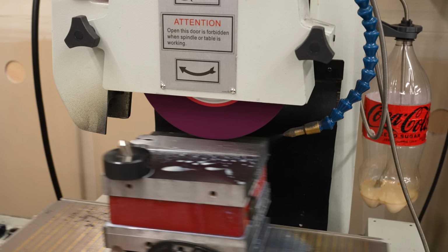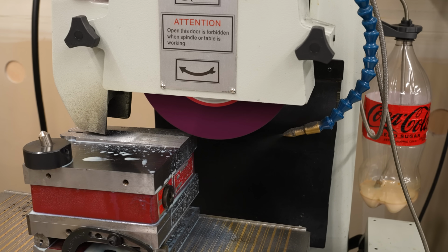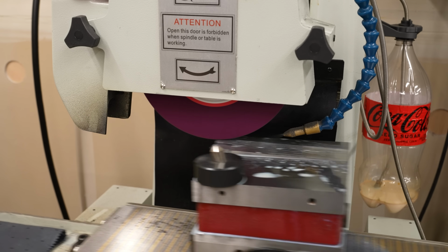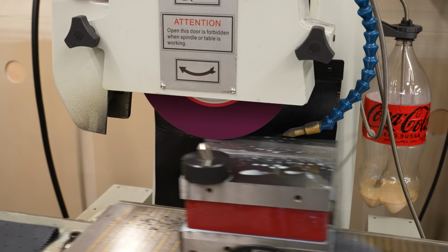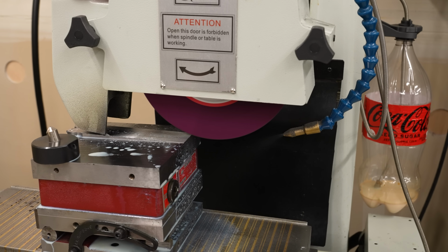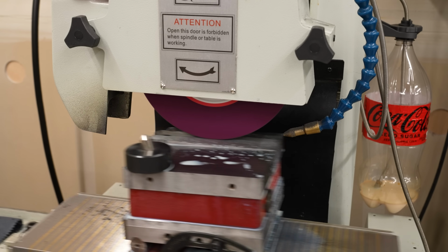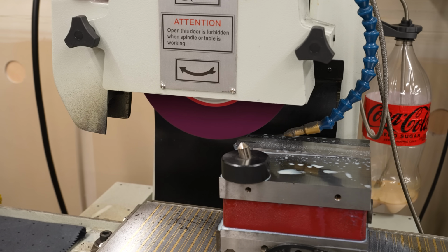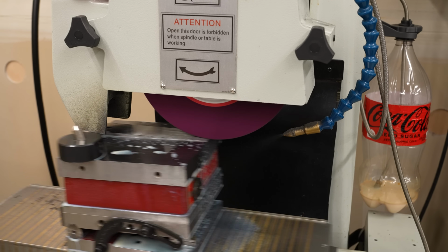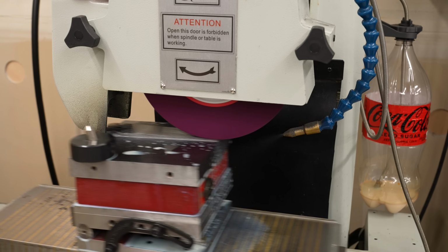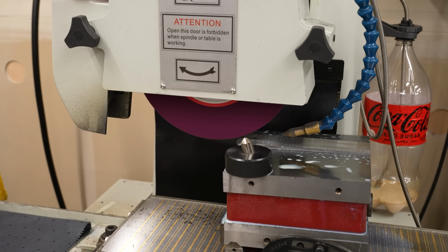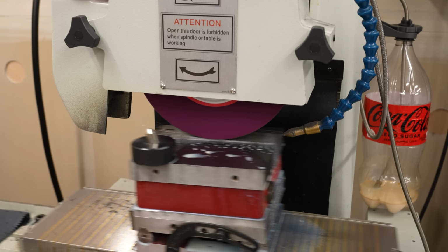The only way I was able to get this to work was to make the coolant mist very, very wet and to go very slowly. For a lot of the finish grinding, I only took 1/10,000th of an inch or even half a tenth or 50 millionths of an inch per pass. With flood coolant, I could probably go faster, but with the setup I have on the machine today, it took a long time to get 3 parts ground flat and to dimension. This easily ended up being the most time-consuming part of the project.